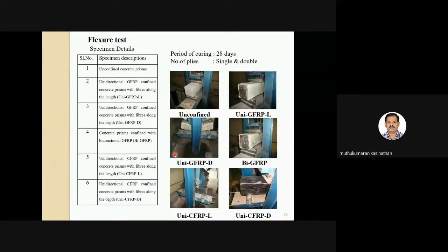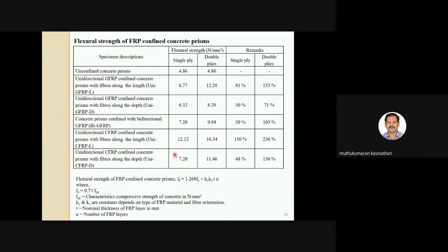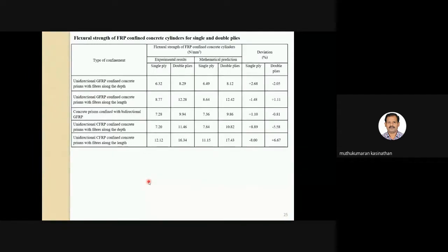Then we have conducted the flexural strength test in a similar pattern. And for the flexural strength of concrete, as expected, using the carbon fiber is much higher than the glass fiber, and the orientation in the longitudinal direction is much higher than the circumferential direction. And based on this data, we have developed another equation for flexural strength. And again, the validation of this equation with the experimental data shows the error is within the permissible limit.